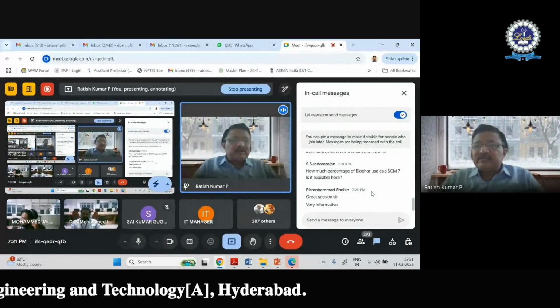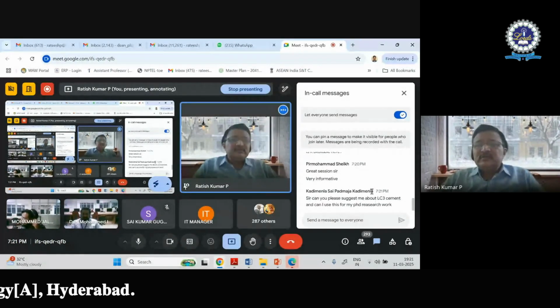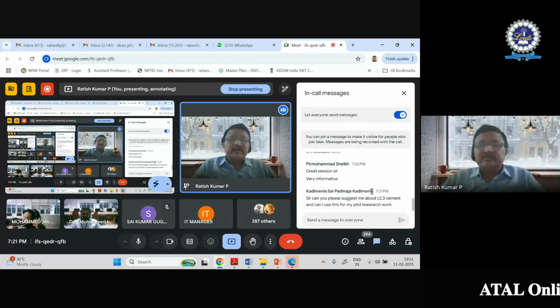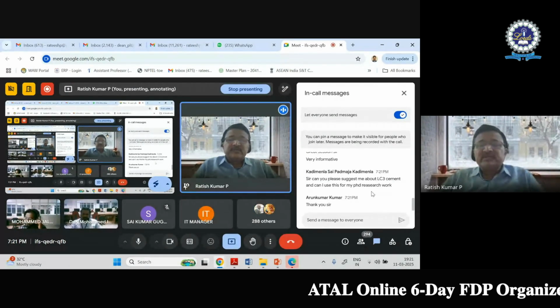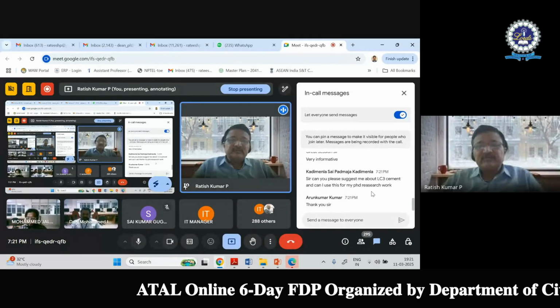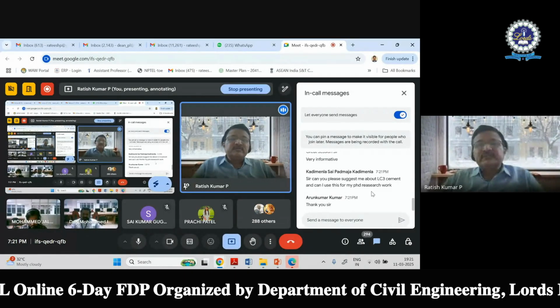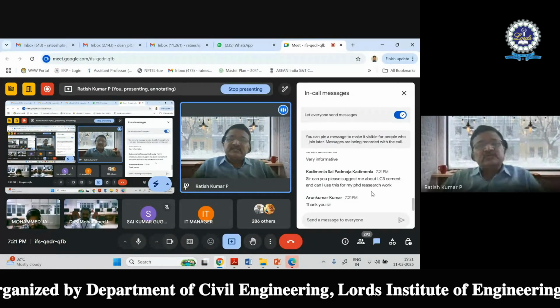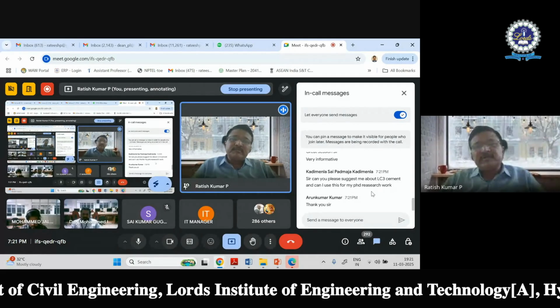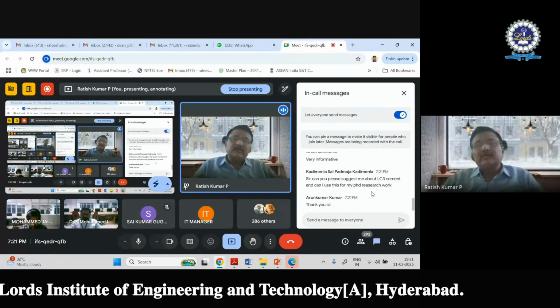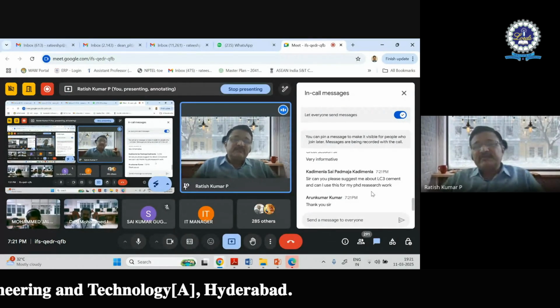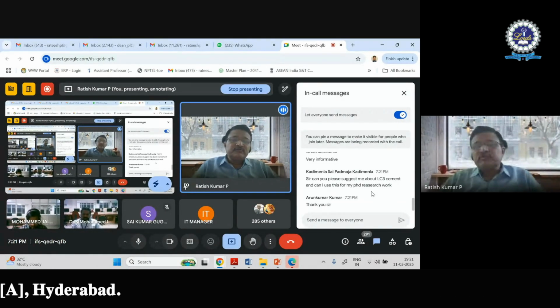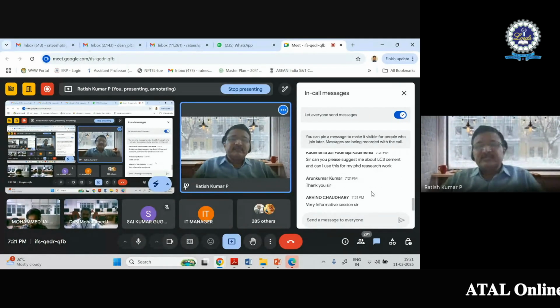Percentage of biochar as an SCM. Yeah, you can use biochar. In fact, you can try to use agro and non-agro based biochars. Somebody is working in the area of fecal sludge biochar also in our case. So we can definitely use that. And then, I think, to the order of 2 to 5%, depending upon peanut husk or peanut biochar or bamboo biochar or different types of biochar, etc. You can use 2 to 5% as a replacement for cement. It has a better benefit.